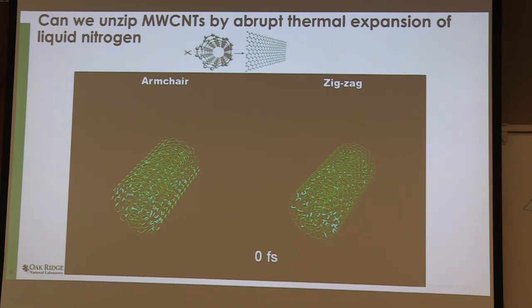So the idea here was, lo and behold, you take a multi-wall carbon nanotube and you put it in liquid nitrogen. You can encapsulate the liquid nitrogen in between the walls of the carbon nanotubes. This can be done experimentally really easily. You just have to be careful or your hands will get frozen when you dip it in there. Actually, you don't do that, it turns out. These are really small. And then you just put it in something hot. Okay, if you put it in hot, guess what happens to that liquid nitrogen? It turns to gas, it expands, and it can't get out because these things are long, so it's not happy. And it would, in principle, rip that thing apart, right? Just explode it like a submarine deep in the water, and split it right in half.